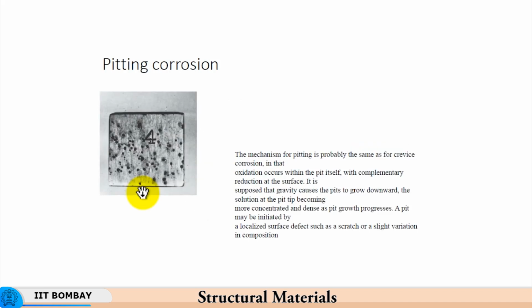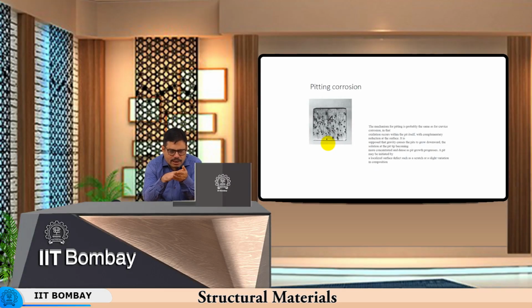Similarly, pitting corrosion is another form of corrosion where the current density is very high. The pits are formed because the current density in the anodic area is very high. So, the size of the anode is extremely small, due to which the current density is more, and so a pit gets formed, and many such pits can be extremely dangerous. So, that is a very important thing to consider. The mechanism for pitting is the same as for crevice corrosion, because once a pit is formed, the continuity of the reaction takes place by virtue of electrons being circulated through the metallic material. They come to the surface where no pits are formed, and then the medium gets ionized into, let us say, H plus and Cl minus, and then these ions further attack it in the pit, because now the current intensity in the pits is that much higher.